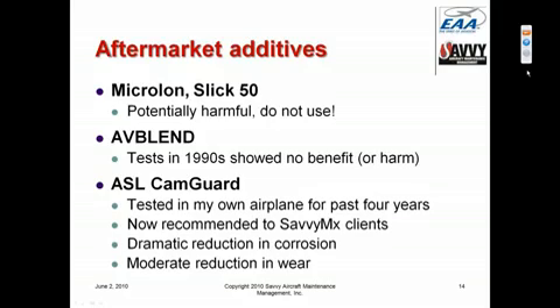If you don't want to use something like CamGuard, then I recommend using an oil that has a corrosion inhibitor pre-blended in it, like Aeroshell W100 Plus or Exxon Elite. But the CamGuard seems to be more effective, at least in the testing that I've done. And so our number one preference is to use a mineral-based oil, typically either Aeroshell W100 monograde or Phillips 20W50 multigrade, with CamGuard added for corrosion reduction and anti-scuff.